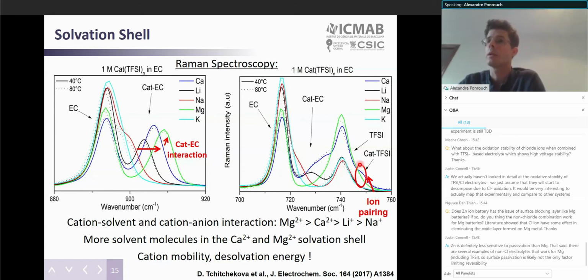The first is the formation of contact ion pairs—the presence of anions in the primary solvation shell of the cations, which can be identified here by a shoulder or a more pronounced shoulder or peak, depending on the amount of contact ion pair being formed next to the peak related to the anion.